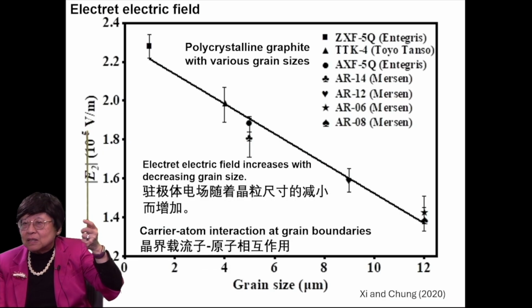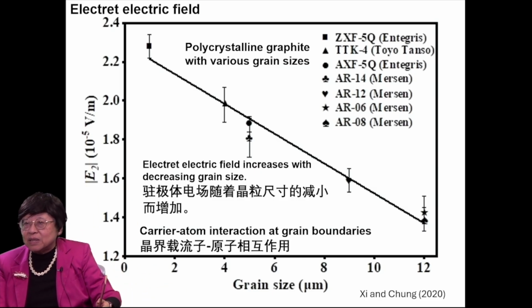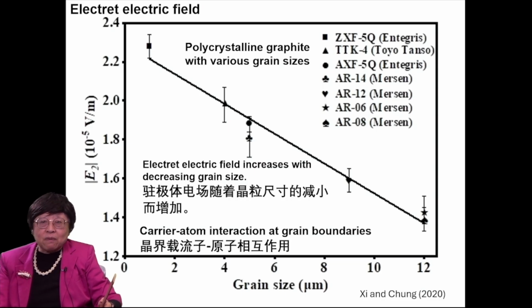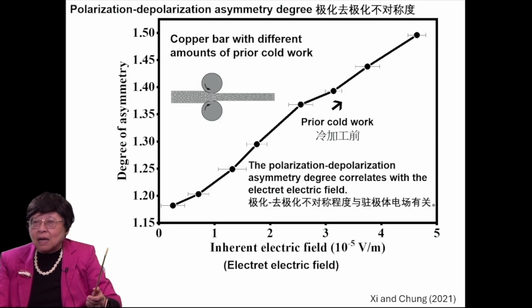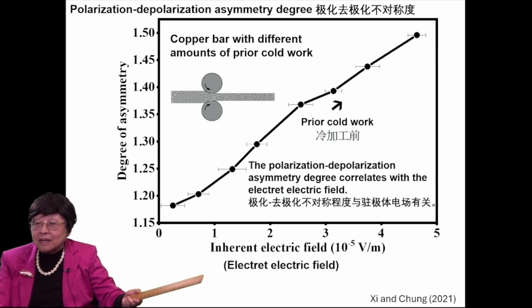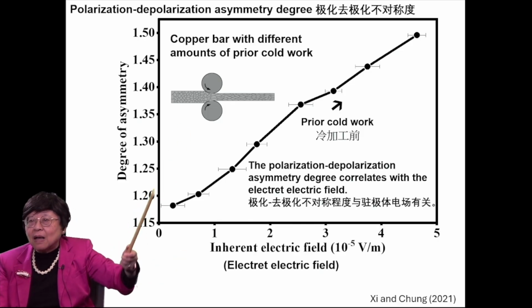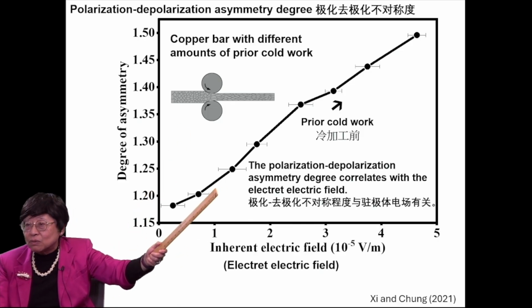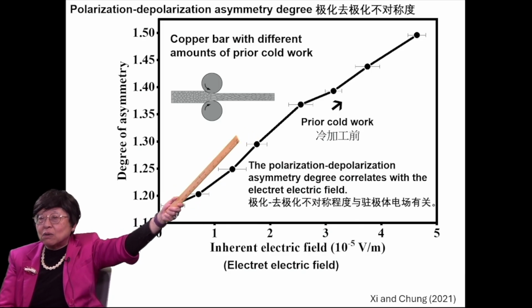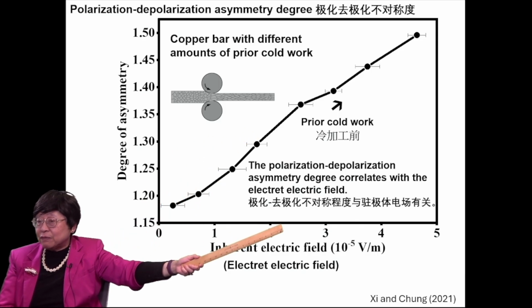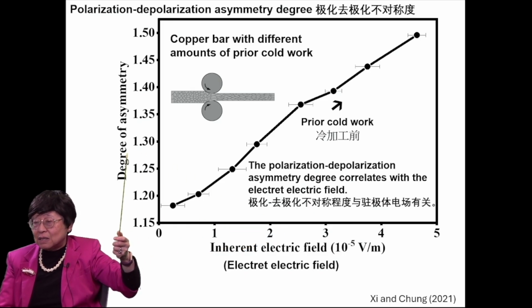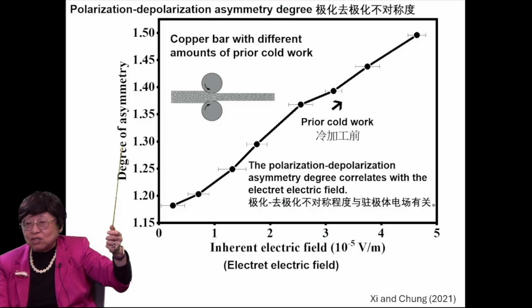And this electric field associated with the electret increases with decreasing grain size, again indicating that the electret involves polarization with the carrier atom interaction responsible for the polarization occurring at grain boundaries. Again, we can look at the inherent electric field for copper after different degrees of cold work or cold rolling. The more is the amount of prior cold work, the greater is that inherent electric field of the electret, and also the greater is the degree of asymmetry in that polarization, depolarization, asymmetry. Okay.